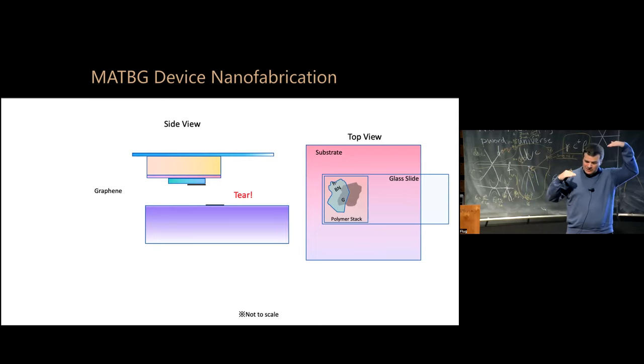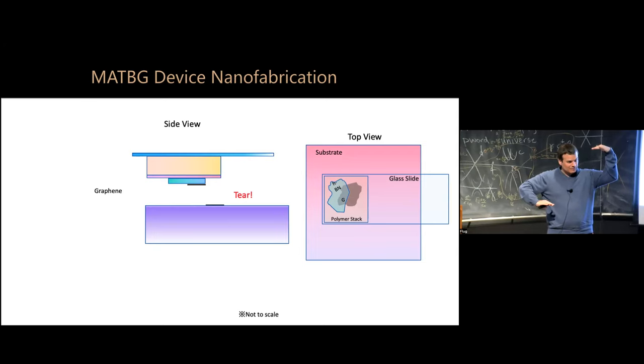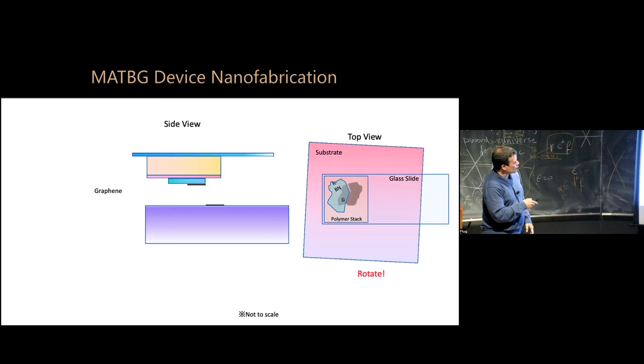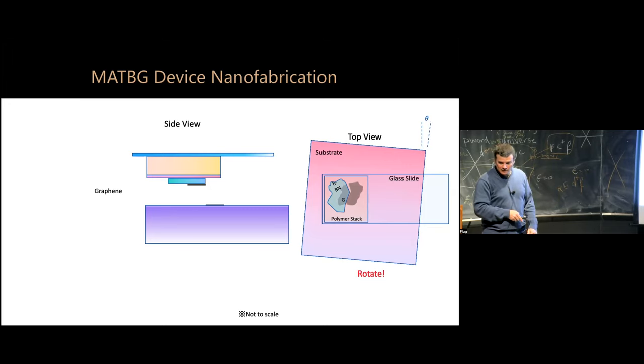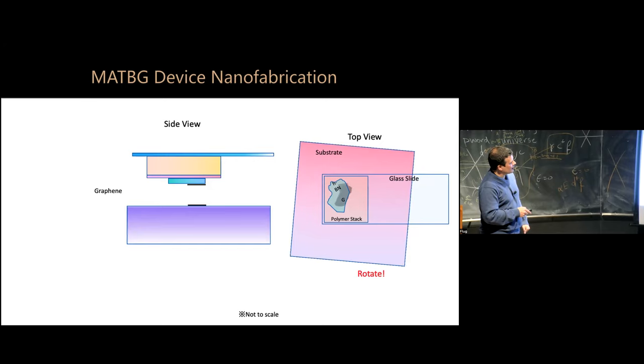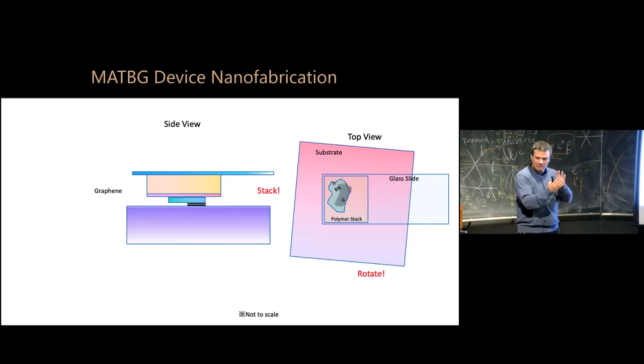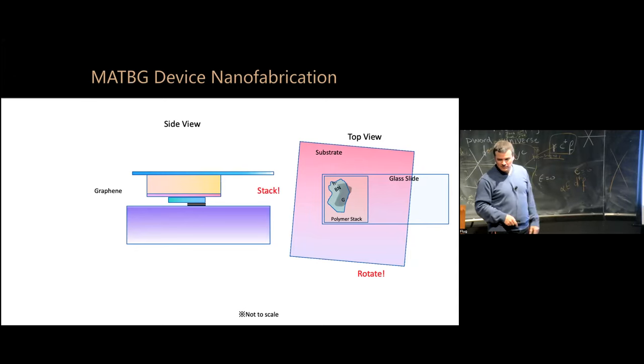But because these two pieces come from the same single crystal, the atoms in one part are aligned with the atoms on the other part, the other graphene sheet. Then I can rotate by any angle that I want. For example, 1.1 degrees, why not? Okay, I can shift this on top and I can stack it. And this is how I form those two atomic lattices, which are at 1.1 degrees. It's this simple, okay? I have high school students that do this in the lab, okay? It's really very simple.